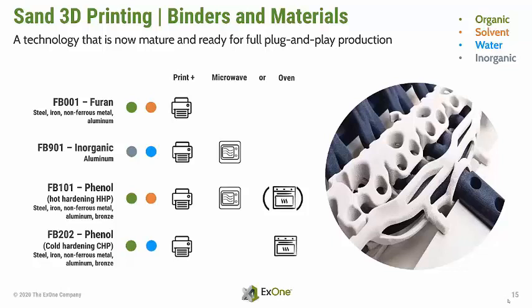The organic hot and cold hardening phenol binder systems can offer even higher strengths and sharper contours of final parts. The cold hardening phenol process requires an oven for individual parts curing, but in the hot hardening phenol process, the whole job box gets cured in a microwave.